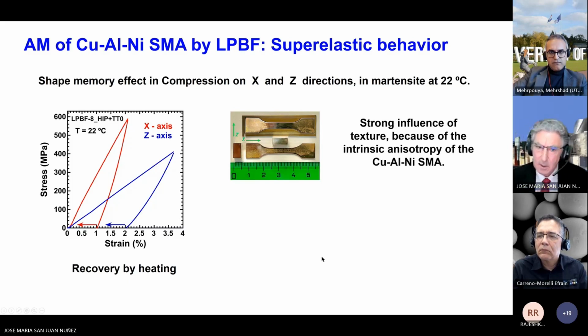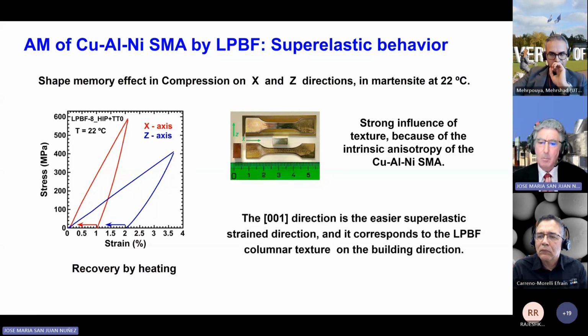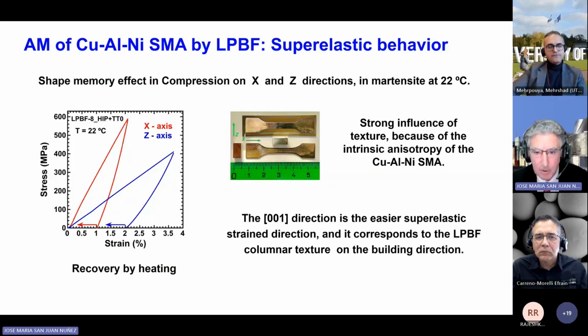So this means that there is a strong influence of texture because of the intrinsic anisotropy of the copper, aluminum, nickel shape memory alloys. And this is because the 001 direction is the easier superelastic strain direction. And we have the chance that it corresponds to the laser powder bed fusion columnar texture on the building direction. So this texture will enhance the behavior of the material.